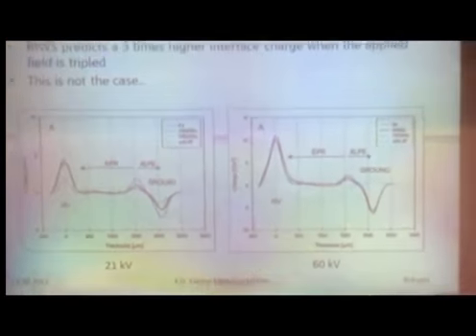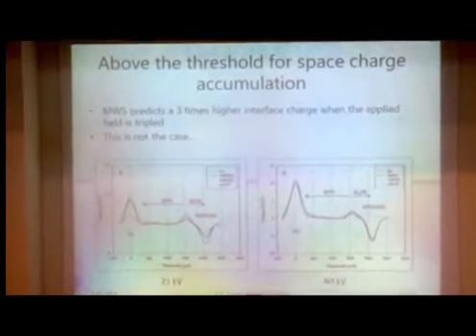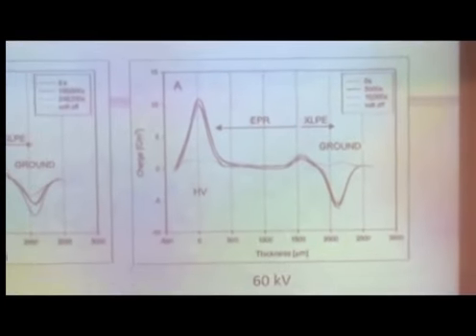To show you that you really have to do that, it's not just theory, I have this example where again we have the system consisting of EPR and XLPE, poling voltage of about 20 kilovolt, then increasing it by a factor of 3. Our model predicts that the amount of charge at the interface would be tripled. Well, evidently it's not. It's even smaller than it was at the lower voltage.